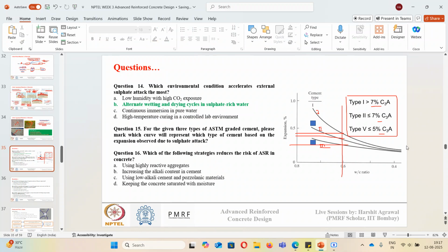Now type 2 cement has lower C3A content, and type 5 cement has much lower C3A content. So curve 2 will represent type 2 cement, and curve 3 will represent type 5 cement. The lower the C3A content, the lesser the chance of sulfate attack, and the lesser the expansion. Expansion is due to ettringite formation, which will swell in the presence of moisture. So that expansion will be less where the ettringite formation is lower, and ettringite formation will be lower where C3A is less.